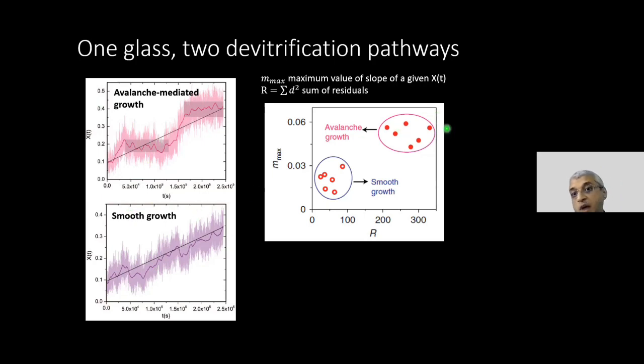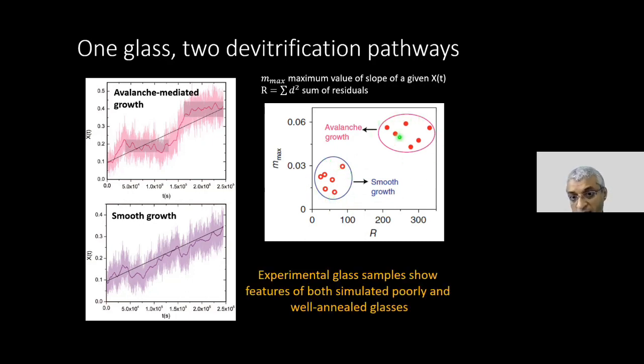And we had about 12 crystallites grow in our sample over the 3 to 4 days over which we tracked the dynamics, and we found that about 6 of them went through a smooth growth process and about 6 of them went through an avalanche growth process. So experimental glass samples show features of both simulated poorly and well annealed glasses. And the question of course is, we have just taken the sample, mixed it and thrown it into the container and started imaging. Why do we see both the pathways in our experiment?